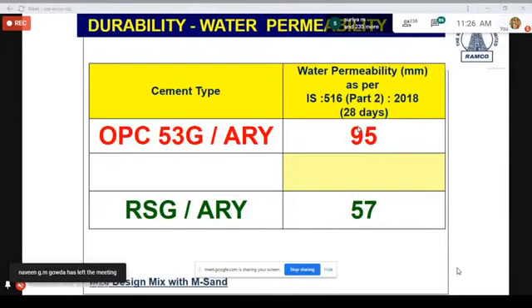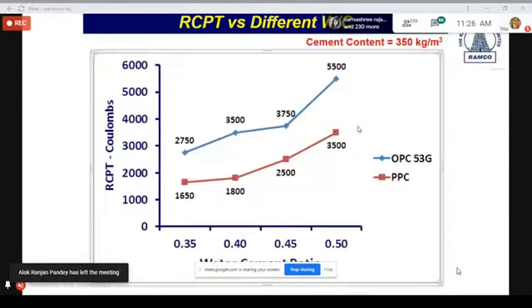RCPT for different water cement ratios. Again, this is the result from our Ramco Research and Development Center. In fact, we have a research center at Chennai where we do a number of durability tests. You will find that at various water cement ratios, this is the ordinary Portland cement. This is the Portland Pozzolana cement. At various water cement ratios, you can find what is the RCPT. In case of ordinary Portland cement, 2750 coulombs, 1650 coulombs. So you can see how with various water cement ratios also the RCPT value changes. It is very important that you maintain the water cement ratio for a better, lower RCPT value. That is what we are looking at.